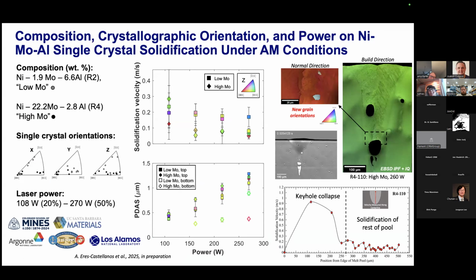So this is now primary dendrite arm spacing versus power. And one thing that falls out of this that is really illustrated nicely for this higher moly alloy is we can see at the bottoms of the melt pools, we tend to see much more refined microstructures as compared to the tops of the melt pool, which is sort of interesting. And so why is this?